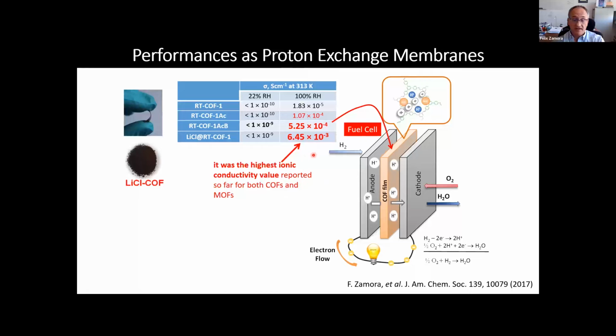But we thought, we have nice high ionic conductivity. Why don't we use these materials as proton exchange membranes in this fuel cell configuration? And for that you need a membrane, of course. And we were able to produce flexible membranes with those having acetic acid in the cavities. But for the case of the lithium chloride, we were unable to form membranes, but we formed a pellet.